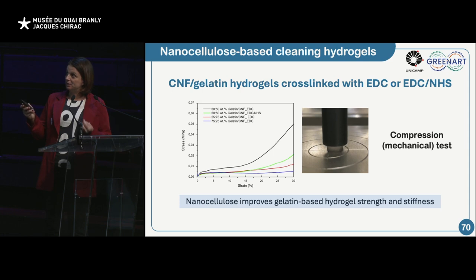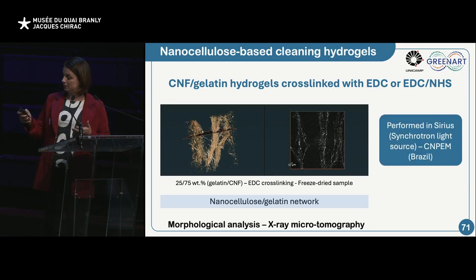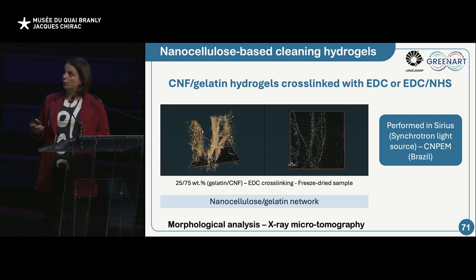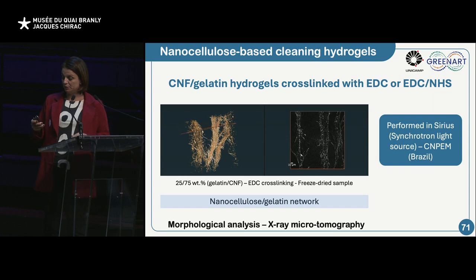We decided this by touching the gels, but we also performed this analysis here, which is a compression mechanical test using a texturometer. So it will give you compression curves with numbers to show basically what we have already seen with our hands. So based on these results, we could see that when we increase the amount of CNF, especially from 25 to 50%, we tend to improve the mechanical stress of the sample. And then we decided to keep working with this 50-50% gel.